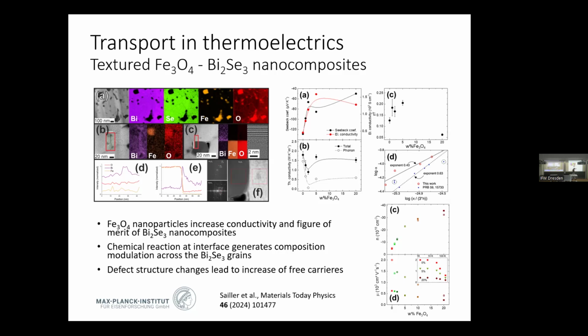However, the Seebeck coefficient doesn't follow the trend of a one-band semiconductor if you change the number of carriers. It doesn't. It's better than the traditional one. Probably because it is not a homogeneous long-range lattice. I would say there is not a periodic potential for all the material, but only partitioned in regions of about 15 nanometers, creating a less than expected reduction in the Seebeck coefficient. All things put together means that this bismuth selenide, which is essentially the same as the one we had before, but with this added component, performs better for thermoelectric reasons, especially for the heavily increased electrical conductivity and the not so deteriorated Seebeck coefficient.